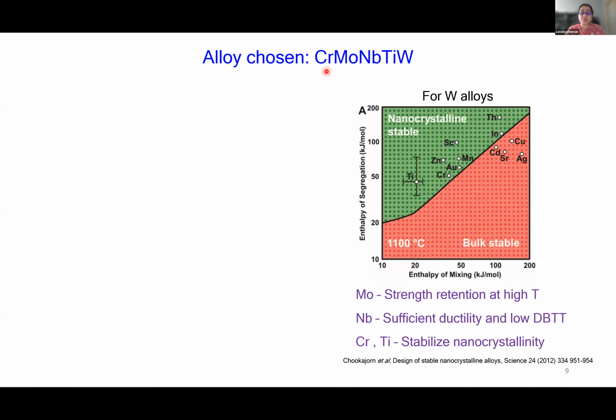To address those questions, we have chosen this composition, which is chromium, molybdenum, niobium, titanium, and tungsten. The rationale for choosing this composition can be understood from this figure. This figure shows work done by Christopher Schuh's group for binary tungsten alloys, wherein they showed that these nanocrystalline binary tungsten alloys can be really stable at around, say, 1100 degrees, depending on the choice of second element.